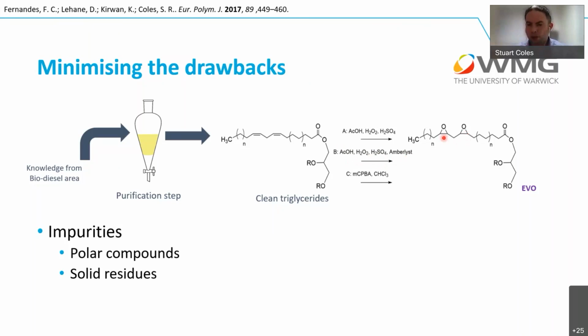You have to be careful with your hydrogen peroxide solution. You don't want too much water and too much acid in there, or you go a stage too far, because you can quite readily ring open that to form the diol, or in this particular case a polyol. So you have to be careful with your stoichiometry and your conditions, but a relatively gentle ion exchange resin works really well, and you can get a relatively clean epoxidized vegetable oil. That itself is not particularly unheard of, because epoxidized vegetable oil, as I already mentioned, is a very large industrial material. We're just trying to do it in a slightly cleaner, more sustainable way.